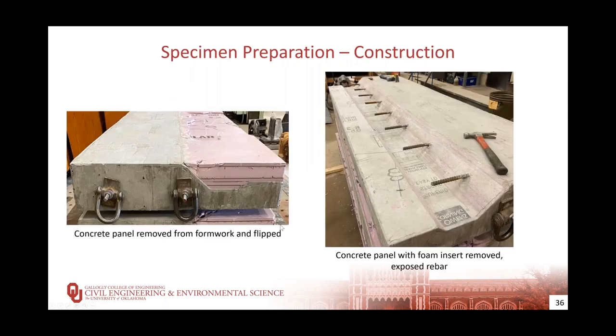The picture on the left is one of the panels after being cast, removed from the formwork, and flipped upright. The foam was removed, leaving the rebar exposed as seen on the right photo. The surface came out almost too smooth, so all the surfaces that were going to be part of the connection interface were sandblasted to roughen them up to promote a better bond.